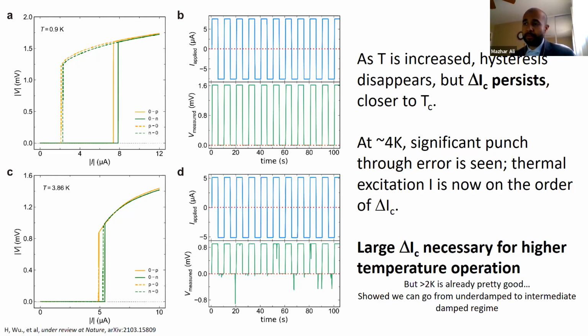I just do want to point out, though, that at least in terms of temperature, we're not necessarily operating at the edge of instability. One nice thing about these devices with these materials, because we can go so thin, only 3 layers, the TC of the stack is almost just the TC of niobium diselenide, so quite high, like 6 Kelvin. Meaning we can easily park ourselves at like 2.5 Kelvin, which is well below the critical TC and not really at the edge of instability.